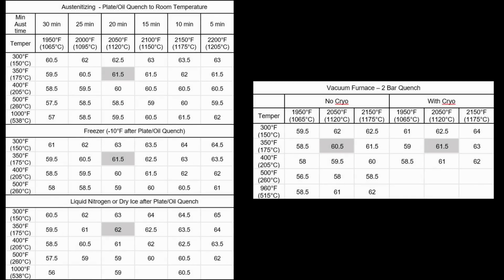The final hardness of the steel comes from several factors. Austenitizing from a hotter temperature or tempering from a lower temperature usually means higher hardness. Cold or cryo processing can increase the hardness another 0.5 to 3 Rockwell depending on different factors. However, even with the same austenitizing, tempering, and cryo setup, the quench rate will affect the final hardness. This is one of the biggest differences between typical factory and typical custom heat treating.